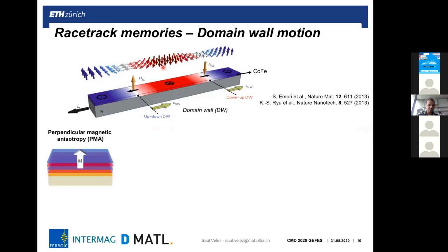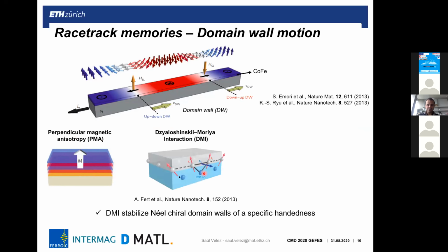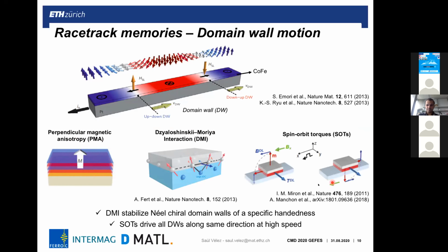So essentially we have three ingredients. The first that we need is to have a perpendicular magnetic anisotropy and the Dzyaloshinskii-Moriya interaction, which allows us to basically break the symmetry and stabilize homochiral domain walls. And this is very important because the sign of the torques depends on the chirality of the layers. And also, we need to use spin orbit torques to drive the domain walls. So then these two, the spin orbit torques and the DMI, can be